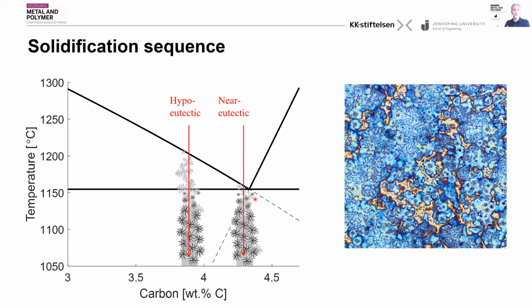This means that they will have a similar concentration of silicon, as we will see later. And if you have a hypereutectic cast iron, then you can have primary graphite, but below a certain temperature, the rest of the structure will grow quite similar to the near eutectic.